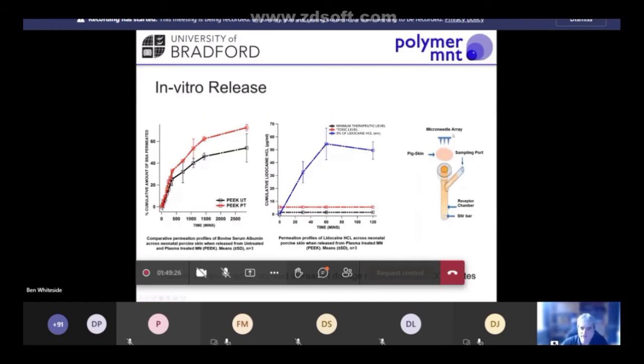So we took our coated array and we did a permeation measurement. Basically we used porcine skin models. We punched our array through the porcine skin and we used a sampling system to HPLC to look at the concentration of BSA that permeated through the skin with time. And we found that when we compare the plasma treated array to the untreated array, we got a significantly higher payload of material coming off the plasma treated. So we were able to achieve a better coating performance by using the plasma treatment for this particular application.